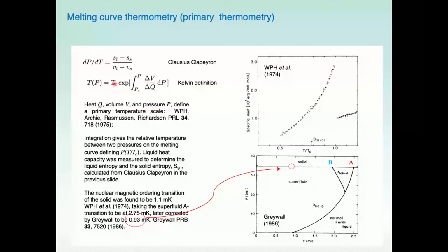This is actually the Kelvin definition of temperature. And if you use this definition of temperature, it's a thermodynamic temperature, you can measure the heat capacity of the liquid helium-3. Remember, it's the liquid helium-3 which forms the thermodynamic system in contact with an interface with solid. Once you have the heat capacity of the liquid helium-3, then you can go back to the Clausius-Clapeyron equation and have calculated the entropy of the liquid helium-3.